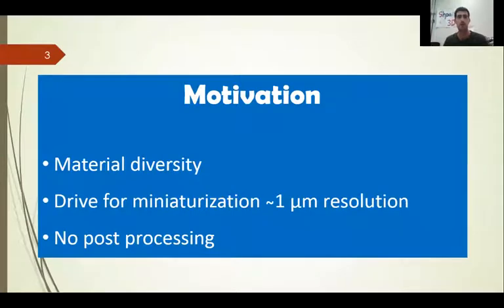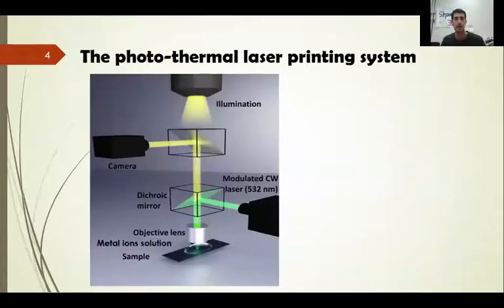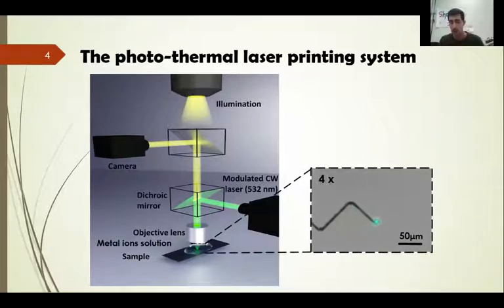So our motivation for this research is first, to develop a new method that could print various materials. We want to reduce the minimal feature size to 1 micron, and we want our technique not to require any post-processing. So how does our system look? We use a modulated continuous wave laser directed to a microscope. The laser beam is focused on the metal ion solution droplet that's placed on the substrate. So in this small area, we get our pattern or structure. Finally, we need only to wash off the metal ion solution and we are left with our